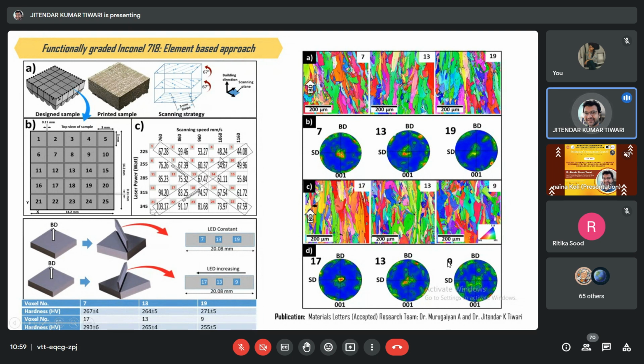Okay, so there are three kinds of functional gradation we can achieve. One is gradation in microstructure, you can achieve gradation in composition, and you can also achieve gradation in porosity. So these three kinds of gradation can be achieved with 3D printing technology. People have done it with conventional technologies, but it is more feasible when we use the laser powder bed fusion technique for metallic materials. So here I have utilized the parametric variation in the laser powder bed fusion process, and achieved the variation in the microstructure.